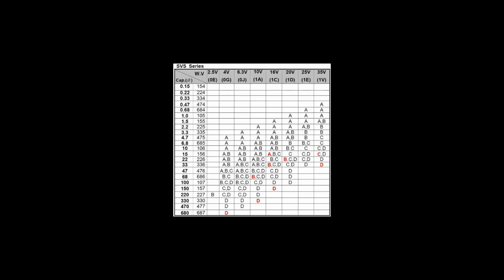Reverse voltage. Tantalum electrolytic capacitors are polarized and generally require the anode electrode voltage to be positive relative to the cathode voltage. With a reverse voltage applied, a reverse leakage current flows in very small areas of microcracks or other defects across the dielectric layer to the anode of the electrolytic capacitor. Although the current may only be a few microamps, it represents a very high localized current density which can cause a tiny hot spot. This can cause some conversion of amorphous tantalum pentoxide to the more conductive crystalline form. When a high current is available, this effect can avalanche and the capacitor may become a total short. Nevertheless,